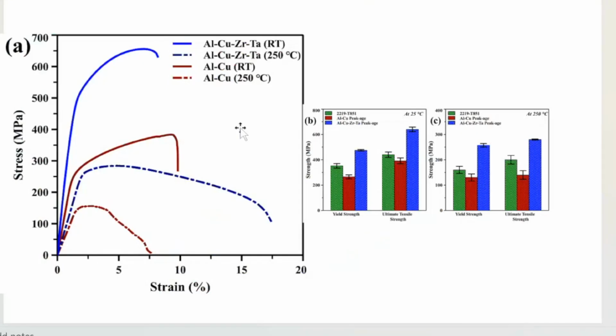Room temperature yield strength is more than 500 megapascal. But at 250 degrees centigrade itself, you get more than 250 megapascal strength. And it has a reasonable ductility. So we concluded that tantalum addition can produce very good high temperature aluminum alloys, together with, of course, zirconium.